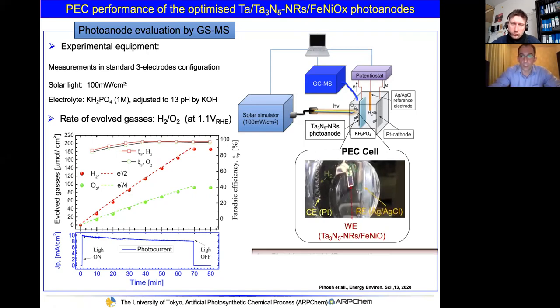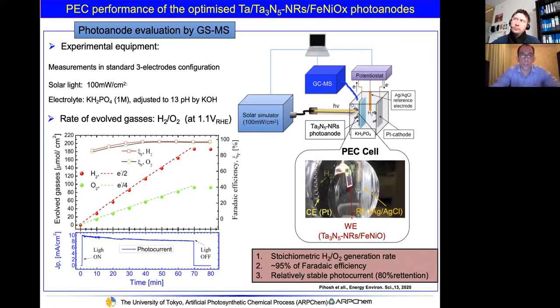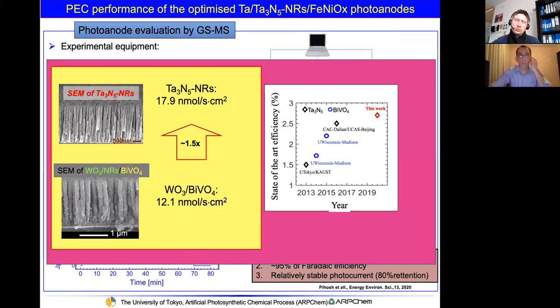So in conclusion to that, stoichiometric fuel generation rate was detected with about 95% of Faradaic efficiency and relatively stable photocurrent of about 80% retention. So it's quite stable. Okay, now if we compare the tungsten oxide, bismuth vanadate core shell structure with just simple Ta3N5 nanorods, we again had an improvement of 1.5. So yeah, this material is really very, very promising.